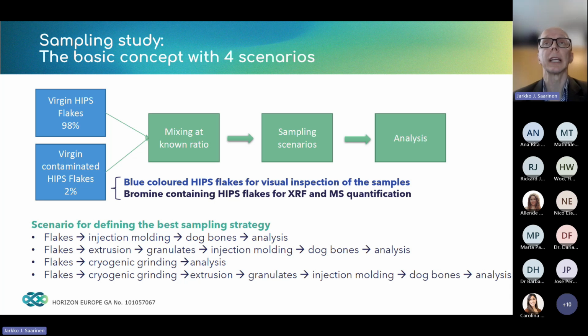Scenario number 3 is the same as scenario number 1, except that we now do the cryogenic grinding of the material. So the flakes have been ground down to the 500 micrometer scale and then mixed. And then also scenario 4 with the cryogenic grinding is similar to scenario 2, except that we do the cryogenic grinding before doing the extrusion and then the injection molding.